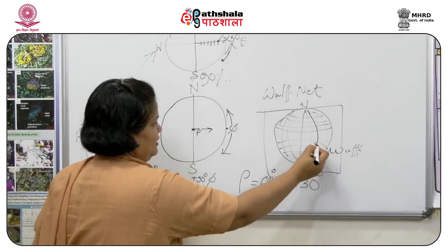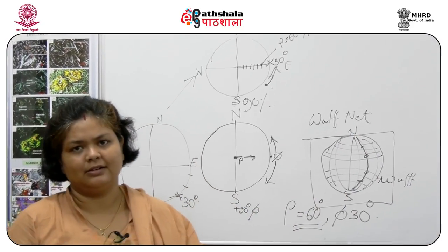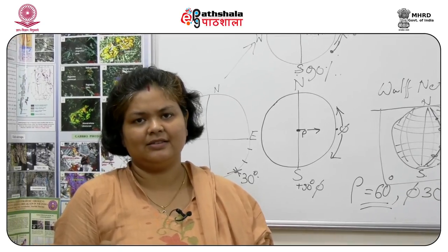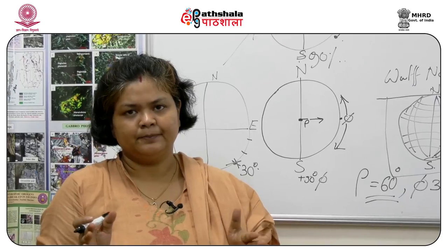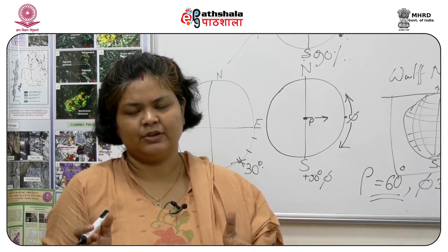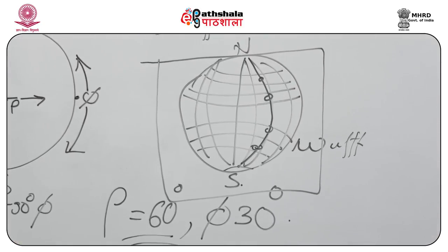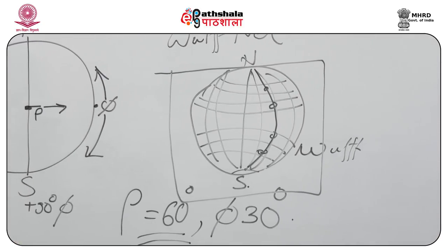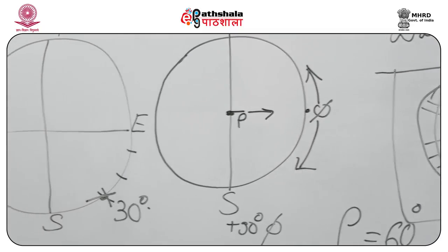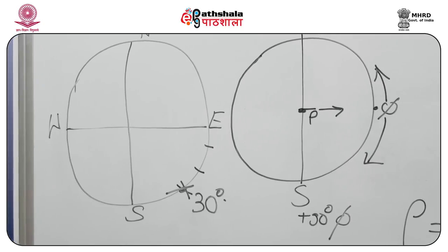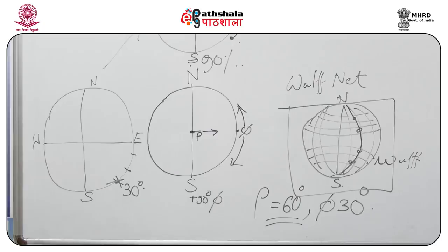So this will be one face, this will be one face, this will be one face. And if they are all plotting on one great circle, we know that these crystal faces must be belonging to a zone. Zone as in crystal faces which share parallel edges. So the applicability of stereo net keeps on increasing, and for stereo projections of each crystal class as well, we can use the stereo net and can make stereographic projections.